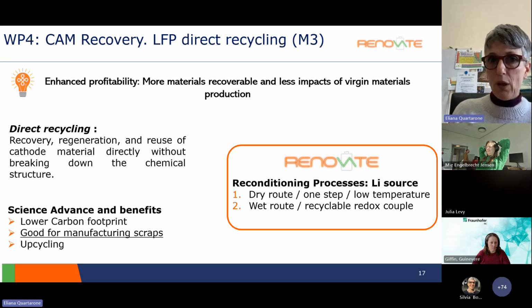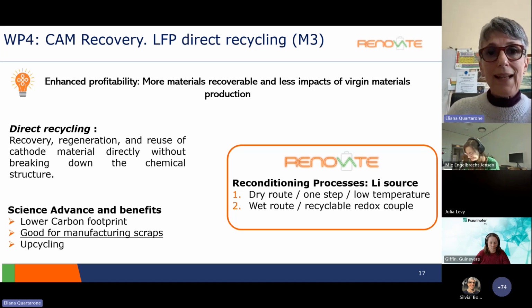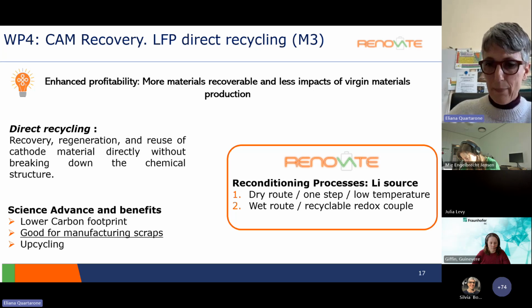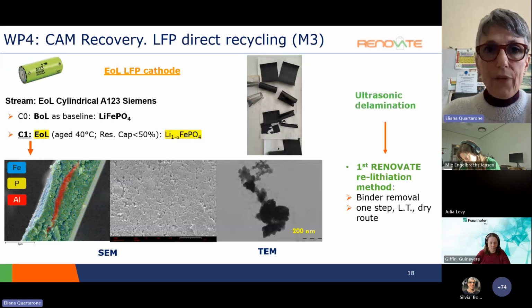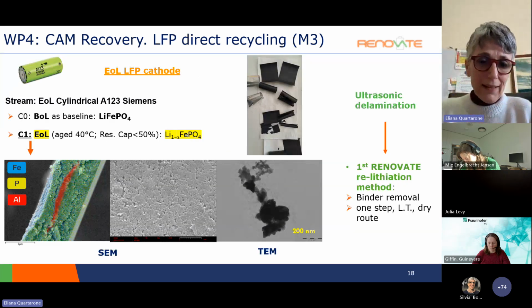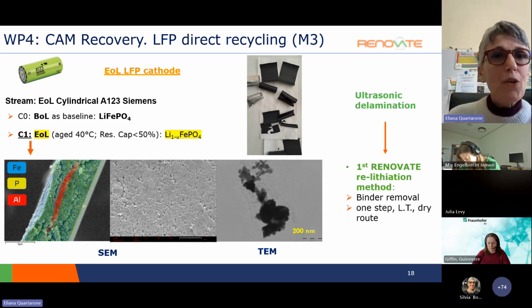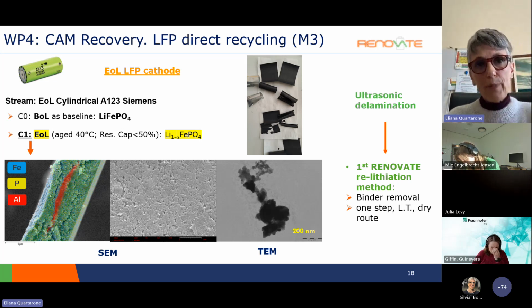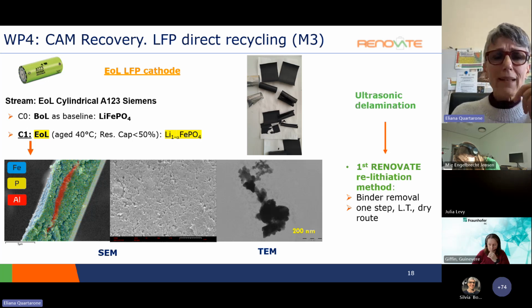One, a dry route at low temperature in order to avoid any additional solvent, and another, a wet route based on a recyclable redox couple. Just a final feedback from the Renovate outcomes is again a work on LFP cathode from end-of-life batteries, but also from manufacturing scraps that we are recovering also by delamination through an ultrasonic approach.